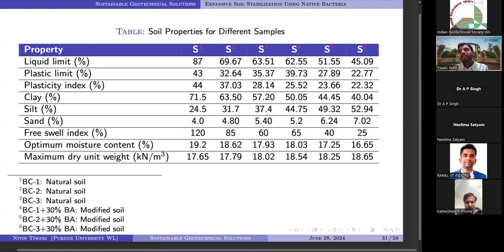Why did we do this modification? The intention was twofold. Number 1, if we are using bottom ash, there is a lot of contamination, and we need to figure out whether MICP also works for contamination immobilization. My colleague Dr. Meghna worked a lot in that area. She published a really good paper in that. And the second point was, if you are using bottom ash, ultimately you are changing the grain size distribution of the soil, and it will be really good for having a MICP treatment for the large grain size material. So this was the idea.